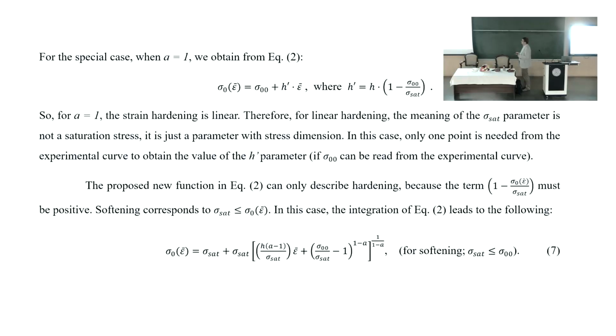But we didn't check how it is working when there is strain softening, not hardening. At high temperatures, it's possible that because of recovery processes, recrystallization and so on, it is decreasing immediately, or after a certain strain, there is a softening. So the softening is also possible to describe with this function, but by construction, this term here has to be positive in the original function.